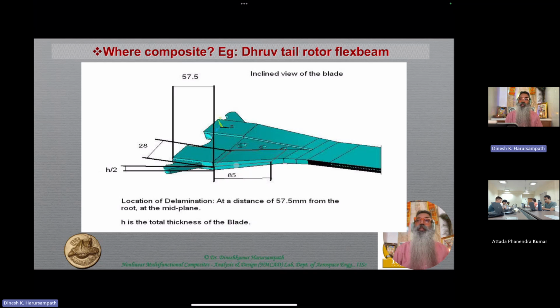So that's the kind of thing that we worked on to create a structural health monitoring system where we put a piezo fiber composite over here, not at 0 degrees, but at 45 degrees, because when you put it at 45 degrees, you get an extension twist coupling that we talked about in the previous class as well. So that ensures the trapeze effect and some advantageous couplings between the pitch control of the helicopter pilot and the centrifugal forces generated because of the RPM of the rotor itself.